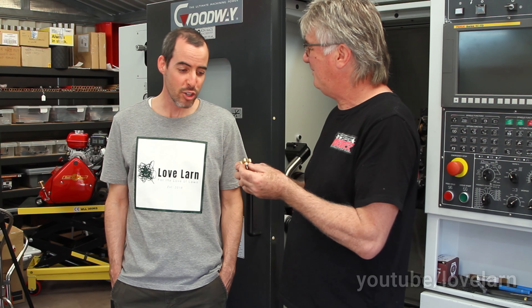So Shane, what material are you making the deflector clamps out of? Haven't decided yet, but either stainless or it's like a gal steel — but it's not galvanized, it's what they use in the motor car industry. Either one or the other, I'll make and stamp them here. We'll look at stainless, but I'm not a fan of stainless on stainless because of the galling issue. Most people treat it the right way, and there's been lots of posts on the resto page about it. We might make the plate out of stainless for corrosion resistance, and a nut can be 4140 and welded to that to stop the galling issue. We'll look at the options when the time comes.